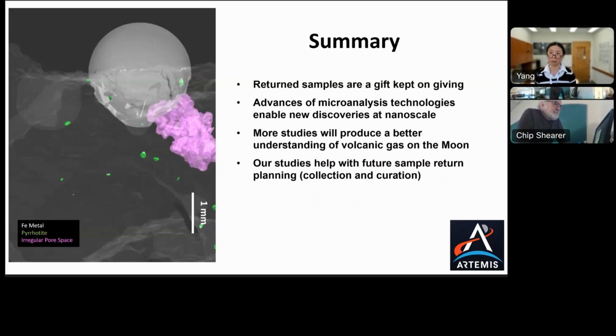Another way maybe, when we have basaltic magma cooling, when there is sufficient sulfur, we can reach monosulfide saturation early during the cooling crystallization of the lunar basalt. And that monosulfide solution will take most of the nickel, cobalt, and copper in the magma into the sulfide. And that sulfide melt will further cool and separate into iron metal and iron sulfide. So that can be another way of separating copper from nickel and cobalt.